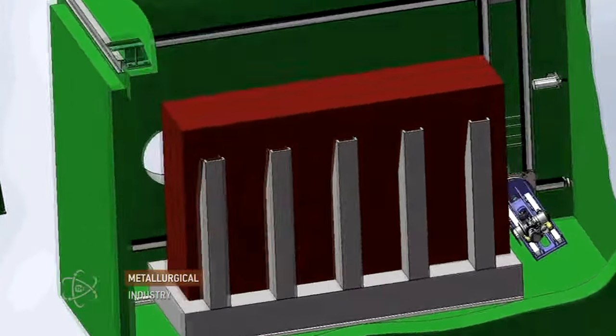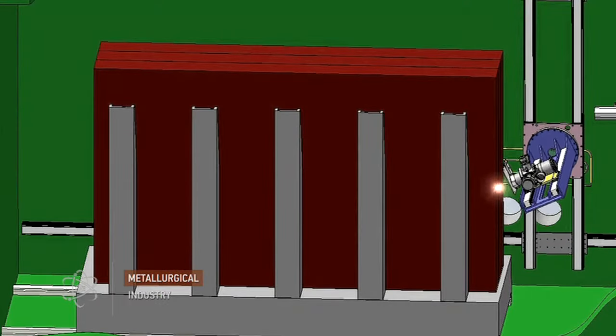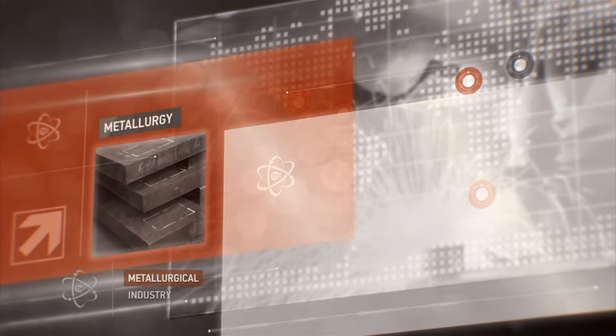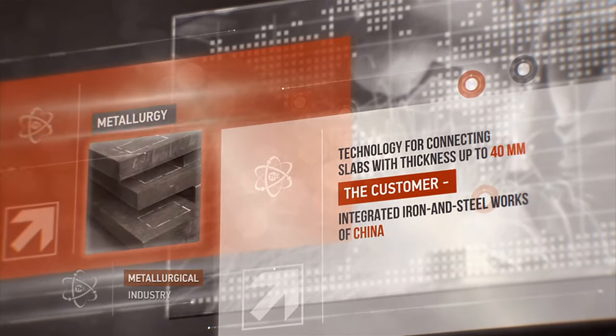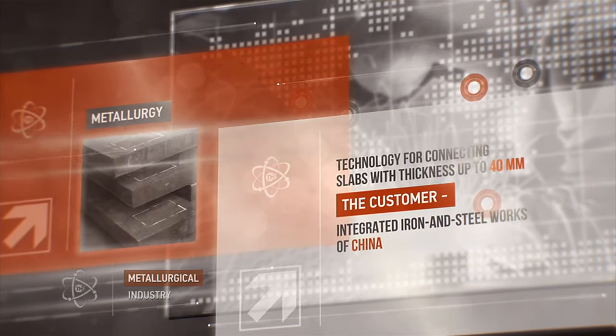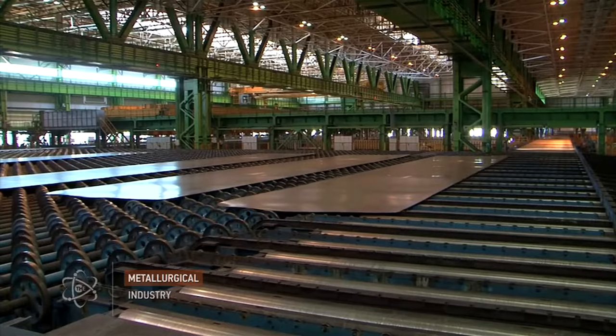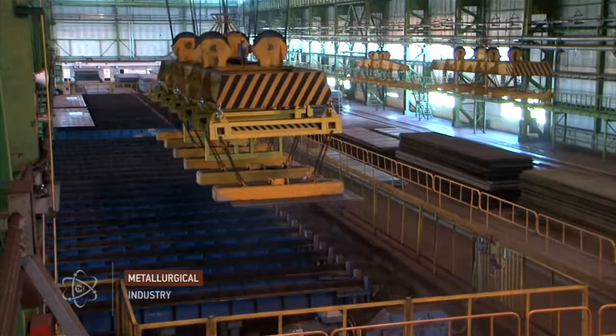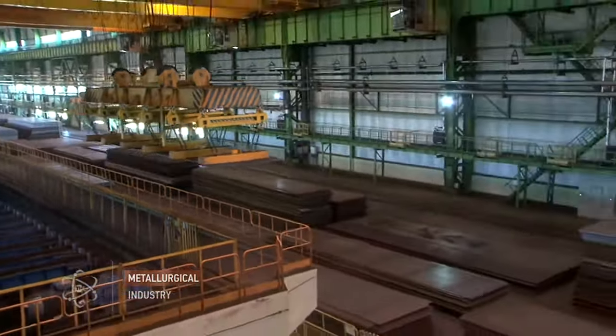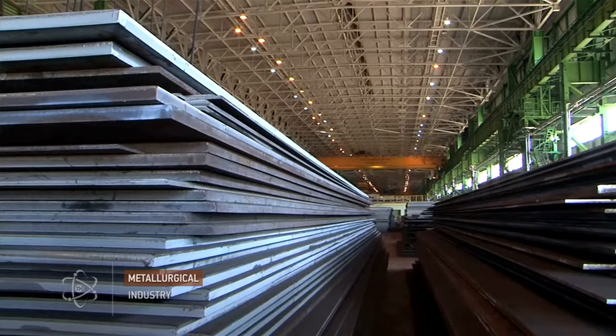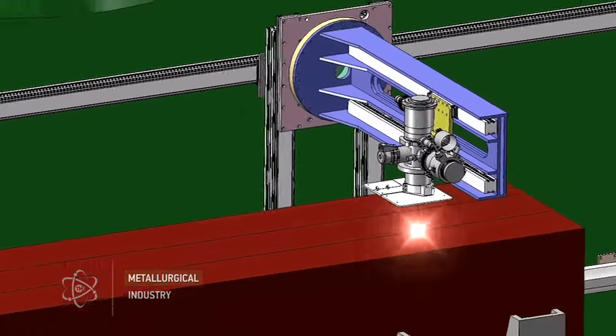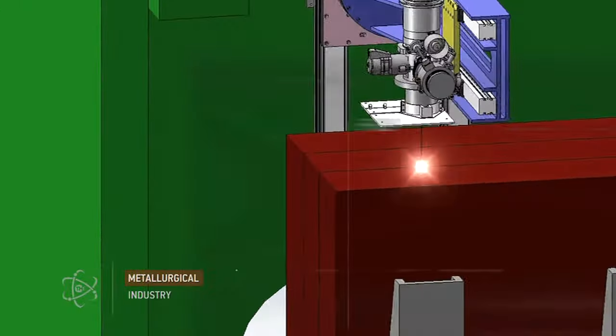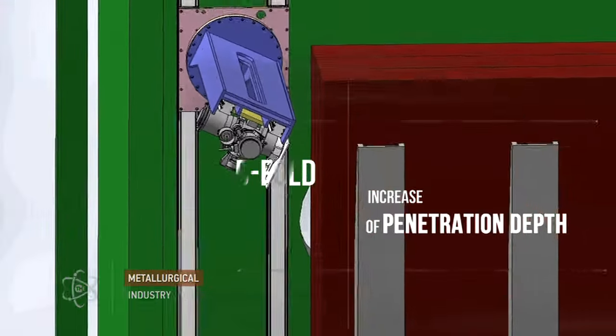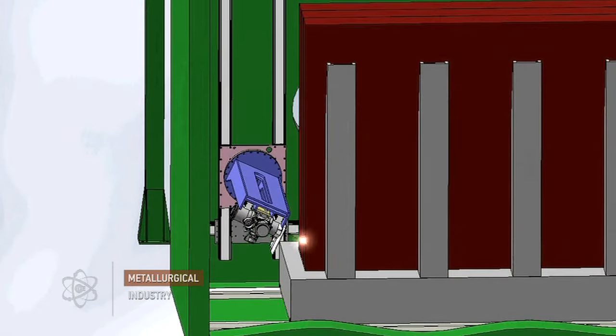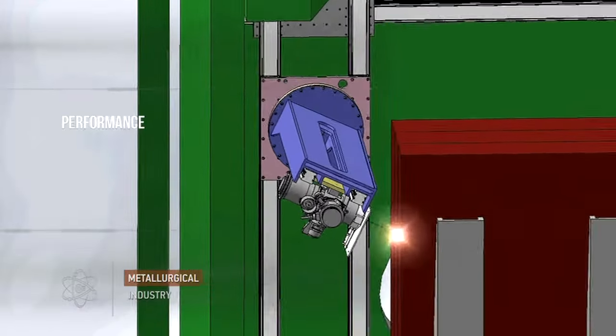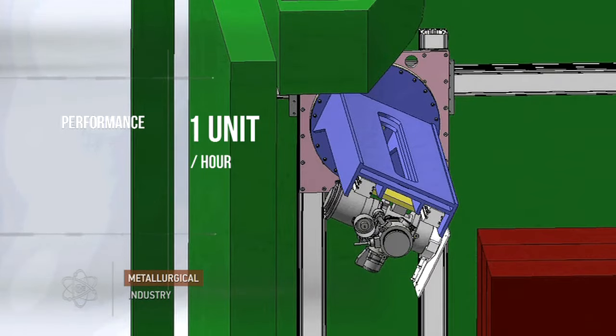Scientists of the B.E.Paton Institute have developed a slab connection method for the metallurgical industry. The customers, a pool of integrated iron and steel works in China, needed to increase the thickness of their slabs from 20 to 40 millimeters. However, they were limited by the rolling mill's capacity. Traditional welding methods did not allow them to obtain homogeneous material because of cavities with air forming inside. Electron-beam welding takes place in vacuum. At the same time, penetration is 5 times deeper than in arc welding. This ensures homogeneity of metal during subsequent rolling and the output capacity of 1 item per hour.